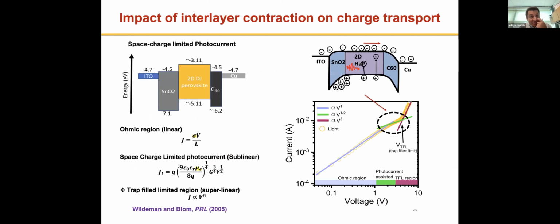And so in order to understand this, we looked at the impact of this light-induced contraction on the carrier mobility and the conductivity. To do that, we performed a space-charge-limited photocurrent measurement. The idea here is that you make a device which only transports electrons, but presents a barrier for the holes. The band diagram is shown here. You can select your layers such that only electrons can go through the circuit, whereas the holes have barriers. And so they create a space charge within this device, and they really impede transport there.